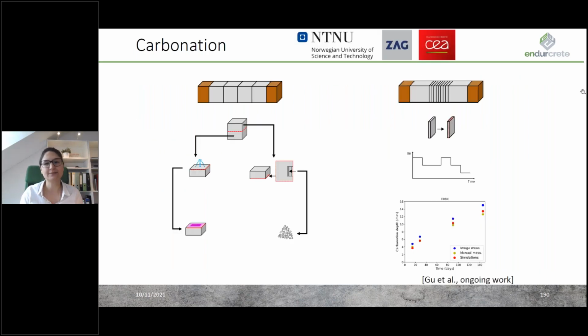And then on top, the other half of these prisms, we cut into thin discs. And half of these thin discs we carbonated fully, and the other half was stored almost CO2-free, a very CO2-poor atmosphere. We then sealed all the non-cut surfaces of these discs and performed drying experiments on them. So we dried them to various relative humidities, always measuring their weight to get an idea of the drying rate. We resaturated them and dried them again to also get an idea of the porosity of the carbonated and the non-carbonated samples. All of this input actually yielded a pretty good carbonation model.